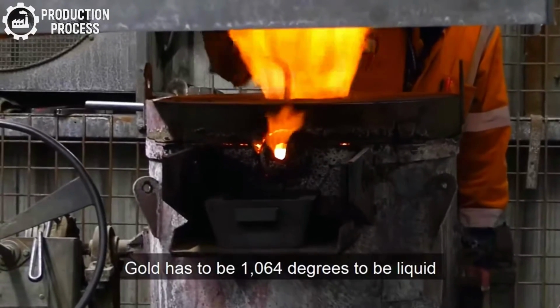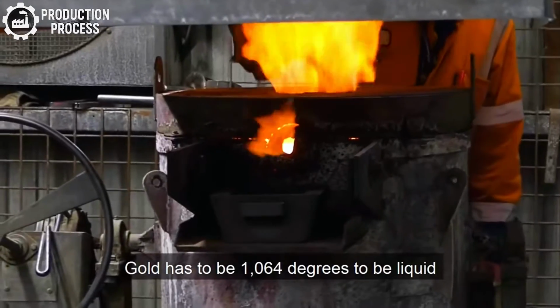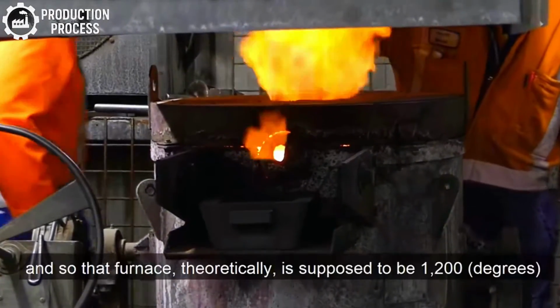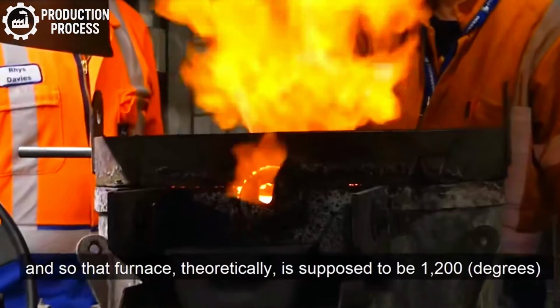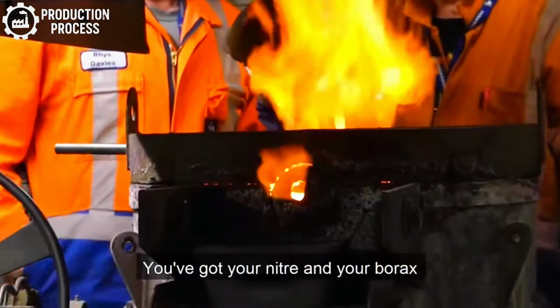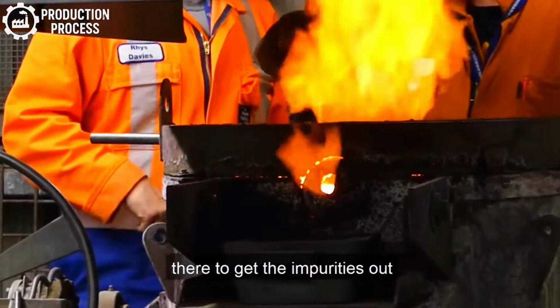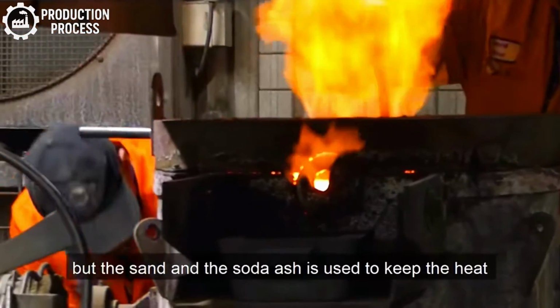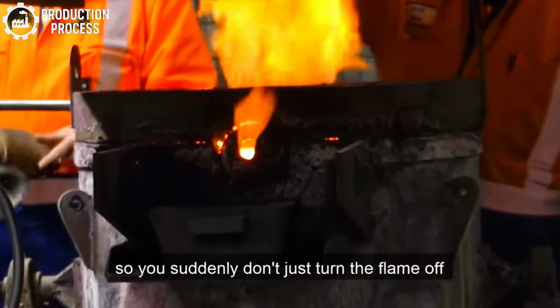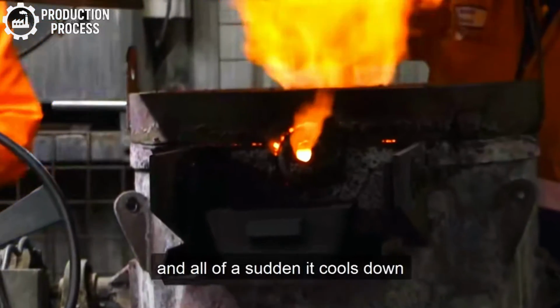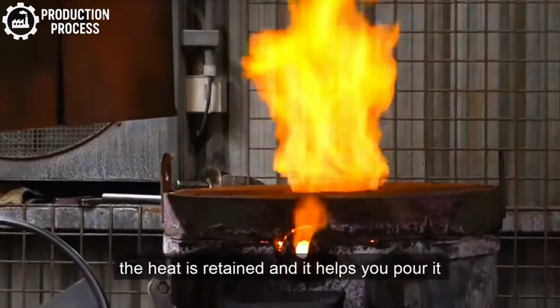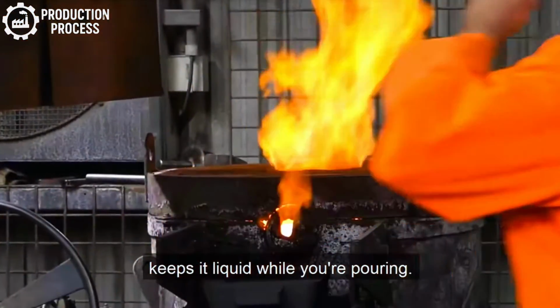Gold has to be 1064 degrees to be liquid, and so that furnace, theoretically, is supposed to be 1200 degrees. You have got your niter and your borax there to get the impurities out, but the sand and the soda ash is used to keep the heat. So you don't just turn the flame off and all of a sudden it cools down; the heat is retained, and it helps you pour, it keeps it liquid while you are pouring.